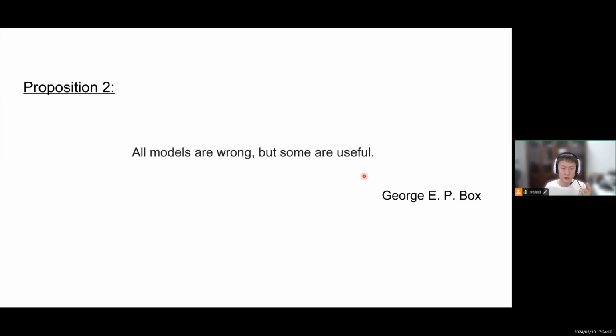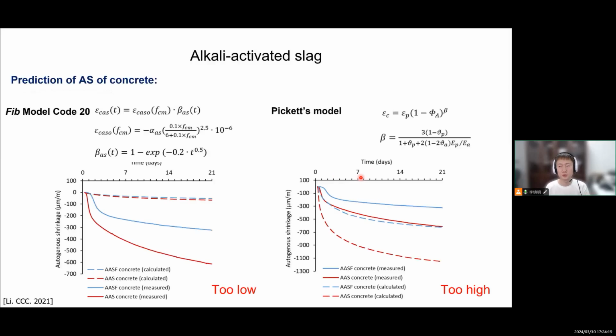So the model we used is useful because it tells us that creep is a very important part of the autogenous shrinkage for the AAS system. So since we know this, we should be able to use this model to predict the shrinkage of alkali-activated slag concrete. For the prediction of shrinkage of concrete, there are already several models available. For example, the fib Model Code. In the standard, we can use the model to predict the shrinkage from the strength data, but this model doesn't work for AAS because for a similar strength level, AAS will show higher autogenous shrinkage. So this kind of equation doesn't work for this material. It will make it very low. It's really an underestimate.